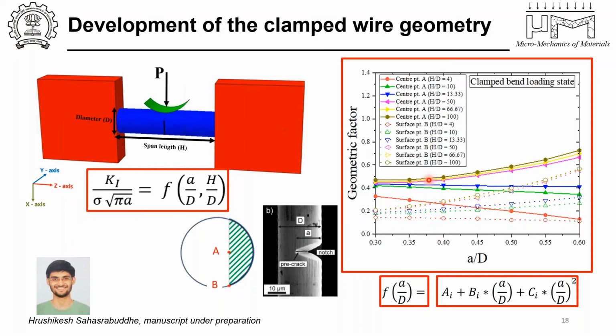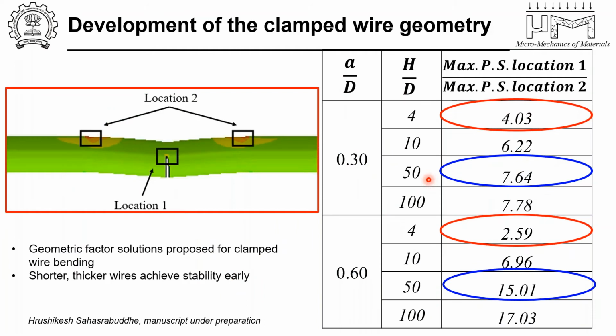But why does it show a difference in terms of the H by D? So what we have plotted here to explain the same is the maximum principal stress at location 1 with respect to location 2. This is in front of the crack tip, and this is at the two fixed edges of the wire or the beam. Now, if you look at a small crack of A by D of 0.3 versus a long crack of 0.6, let's say the crack grew from 0.3 to 0.6. Then for a small aspect ratio wire, the max PS in fact decreases at the center from this ratio of 4.03 to 2.59. Whereas for a longer wire of, let's say, 50 or 100, the max PS at the location 1 increases from 7 to 15.